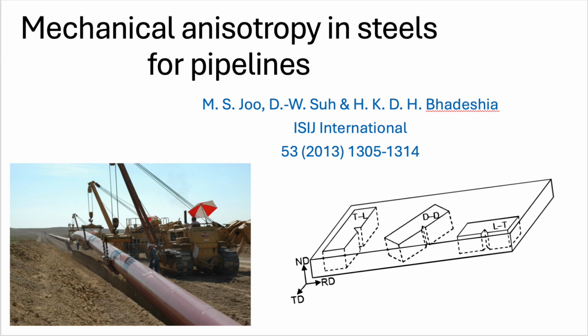That sounds like another built-in weakness. It definitely is. It's a major source of microstructural anisotropy. And it can lead to a visible phenomenon during testing called splitting or delamination. You actually see separations opening up parallel to the rolling planes. Splitting. Okay, but then there's this toughening paradox, as you mentioned. How can splitting be good?